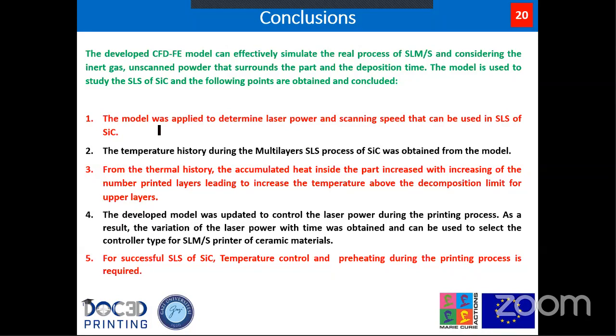And also it is important to include preheating for the chamber, because the sintering point or the melting point for ceramic material is very high, more than 2000 Celsius. To reach the temperature from room temperature to 2000 is a very large jump, and cracks will develop. So we need to reduce this difference by preheating. So it is important to apply preheating for ceramic material.